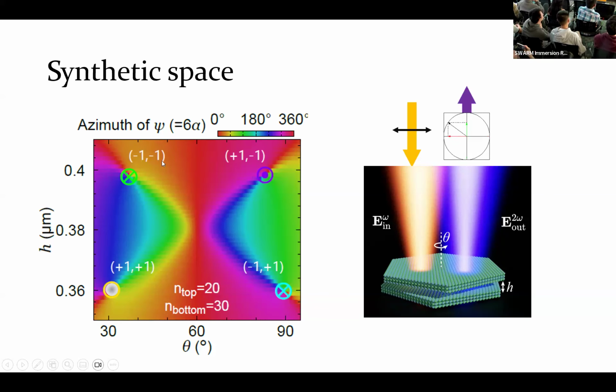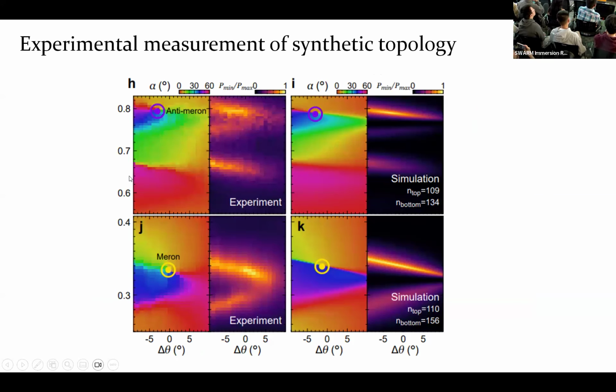And now these are theoretical explanations, but we can actually verify all of this in an actual moiré 2D sample, and we can continuously tune these two knobs of the twist angle and H, so we can actually see these singularities, and it's analogous to the so-called meron and anti-meron in physics.